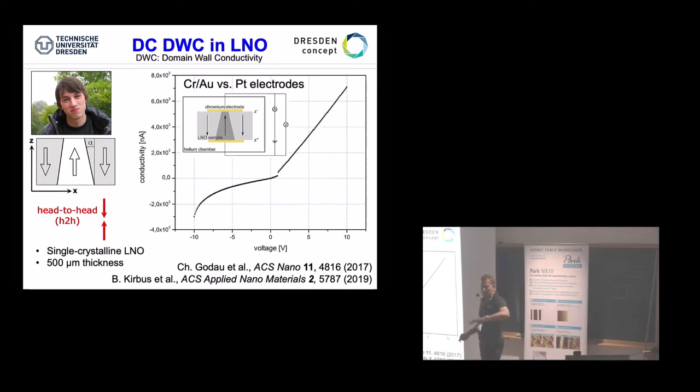On the bottom side, since you can flip over for contacting, it's pure platinum. So we're producing Schottky barriers, where the injection from the electrode into your domain wall is different on both sides, and hence that is reflected by this kind of asymmetry. What is clear to mention at this point is that we've done the engineering in such a way that you see nicely the inclination alpha that we have here points towards a so-called head-to-head orientation.